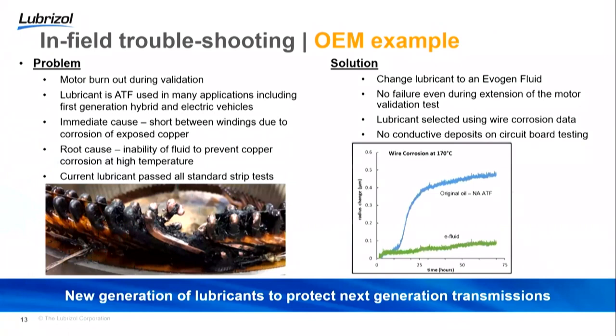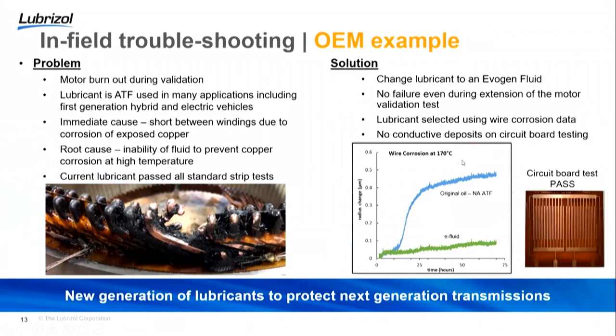And you can see here the results for the E-fluid versus the ATF in the wire corrosion test. This was at 170 degrees, quite a high temperature. And here's a picture of the circuit board test. And you can see a really nice, clean circuit board. An example where, for the next generation transmissions, the next generation lubricants.